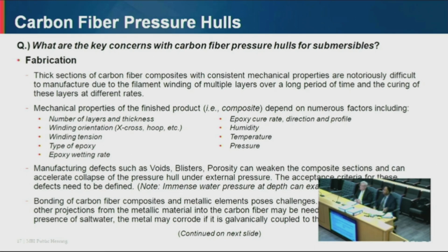Okay, so the other aspect is manufacturing defects such as voids, porosity, blisters, and inclusions, which can have an effect on the strength of the carbon fiber composite. Voids are air pockets within the thickness of the carbon fiber composites. Blisters are formed on the surface of carbon fiber composites. Then you can have porosity. Porosity means a large number of voids in close proximity to each other. All of these can weaken the carbon fiber composite sections, and under extreme hydrostatic pressure, they can accelerate the collapse of the pressure hull.